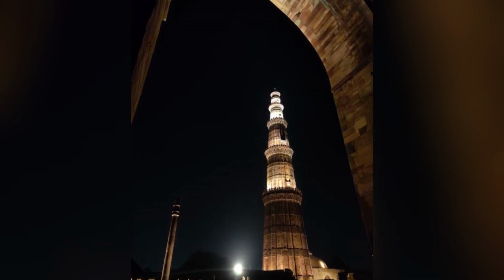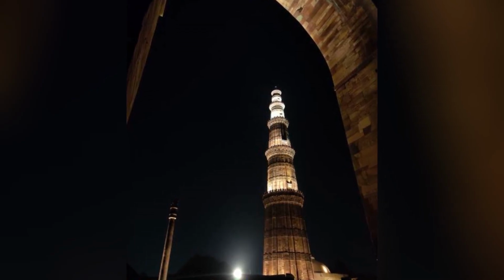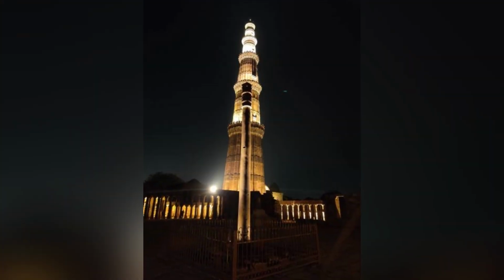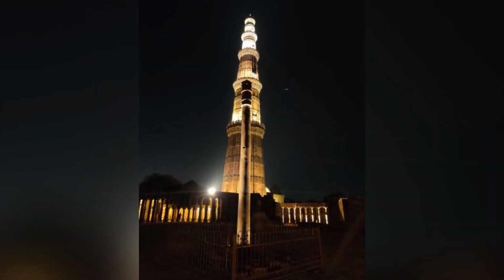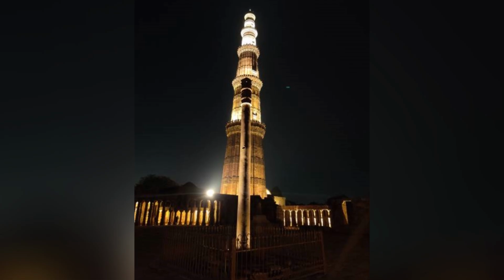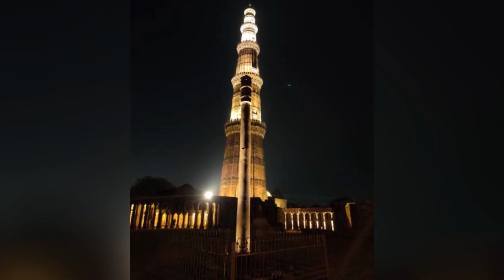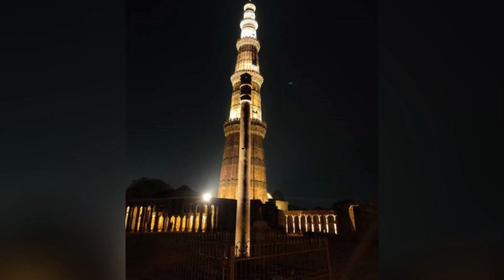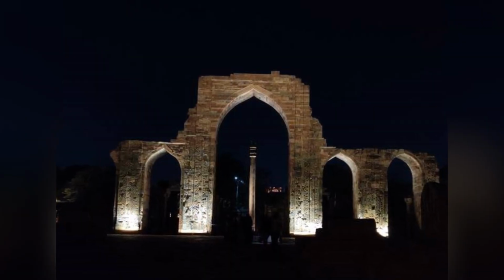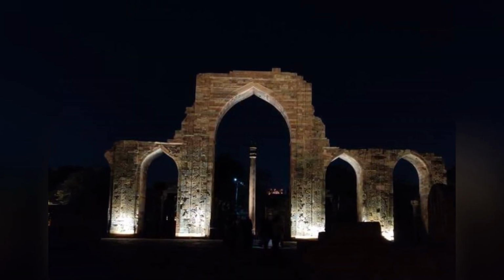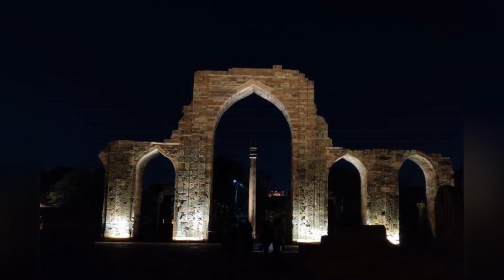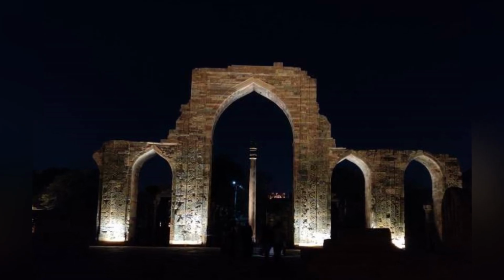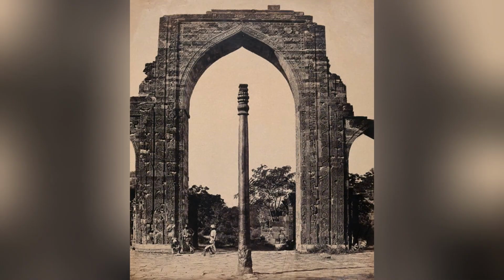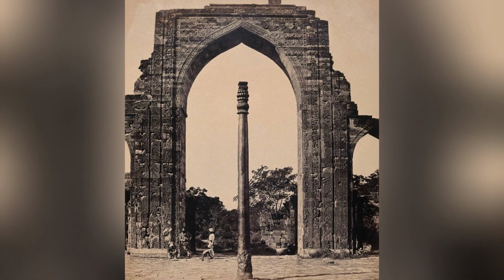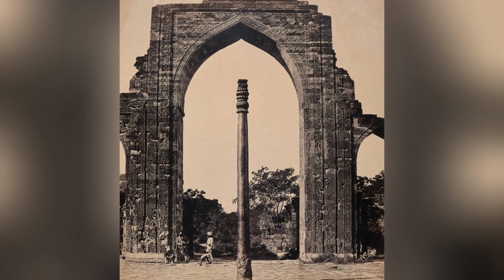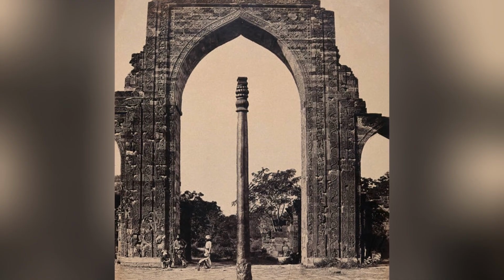The distribution of the slag inclusions within the iron is not uniform, but follows a pattern that reflects the specific techniques of forging and welding that were used to construct the pillar. The slag inclusions are concentrated along the interfaces between the original blooms, the surfaces where the blooms were welded together during the construction of the pillar, and they are less numerous in the centers of the original blooms, where the forging process was most effective in expelling the slag.